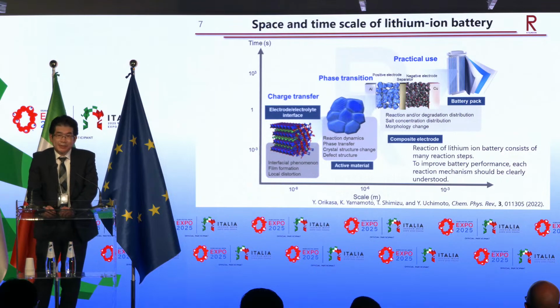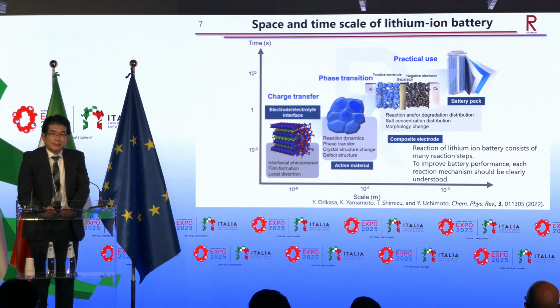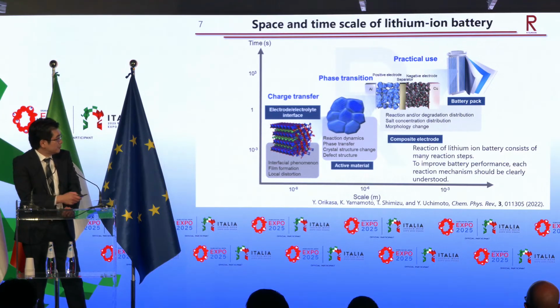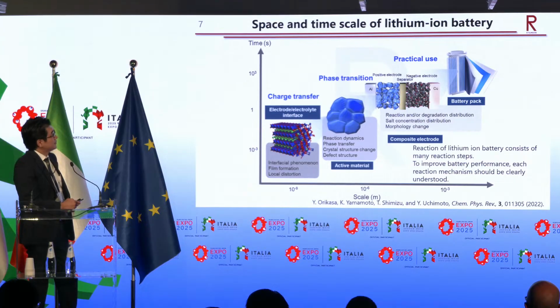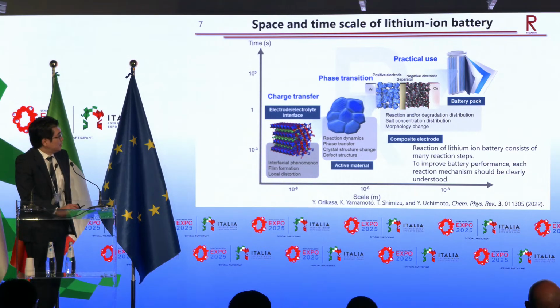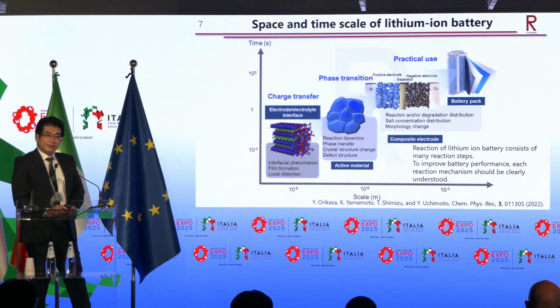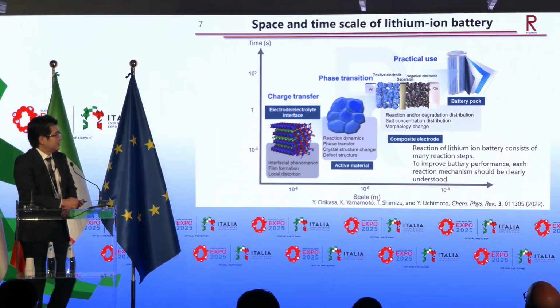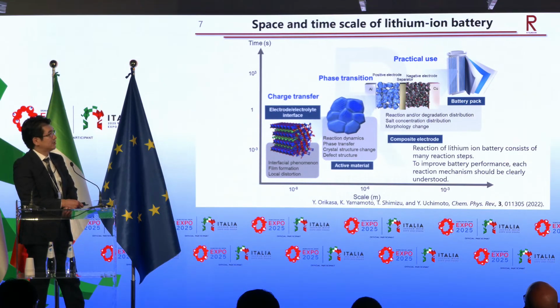So to improve the battery performance, we have to know the elemental reaction based on the electrochemistry. This shows the space and time scale of reaction of lithium-ion battery. So the X axis shows the spatial scale, and the Y axis shows the time scale. The starting point of the electrochemical reaction is the electrode-electrolyte interface, where the charge transfer reaction occurs. And then, for the lithium-ion battery case, the lithium ion is stored in the active material, which is about 1 micrometer or 10 micrometer scale.